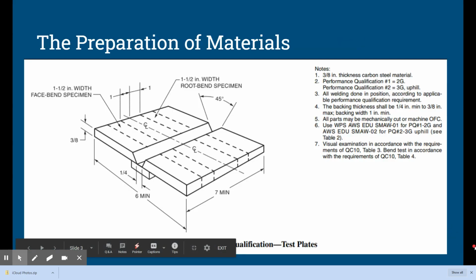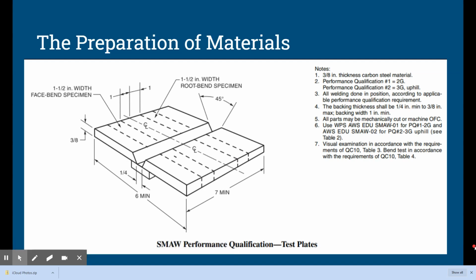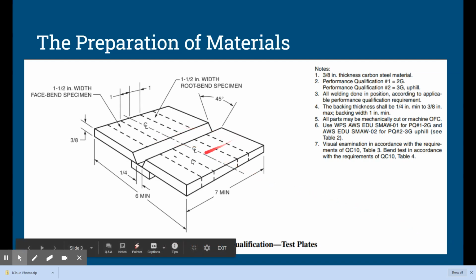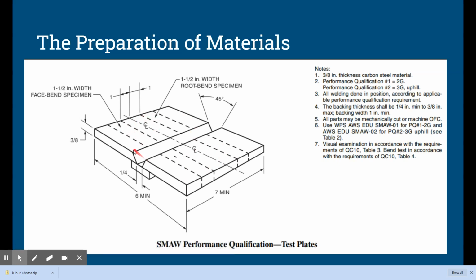So this document is straight from the AWS SENSE Program Guide. You can see this is ultimately what we're trying to do. We've got two separate pieces of metal here. We cut bevels on both of them or on one of them, depending on the weld that we're doing. We tack them to a backing strip. Now here they show the backing strip being flush. I like to extend my backing strips out a little bit farther to have a place to start and finish the weld on. And then ultimately, we're going to be cutting these testing strips out of here, and bending them to test the quality of fusion at the weld joint.